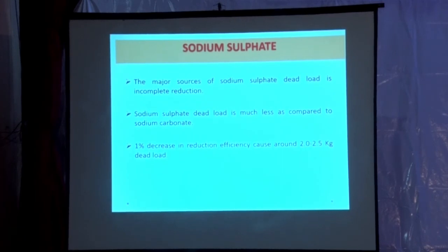And the first and most important term is the temperature. So fixing a char bed height and fixing a temperature at the hearth has to be done to get the maximum possible reduction. Mills are achieving 94%, mills are achieving 95%, but there are certain larger mills having 80%, 82%. You know that you are adding to that load.